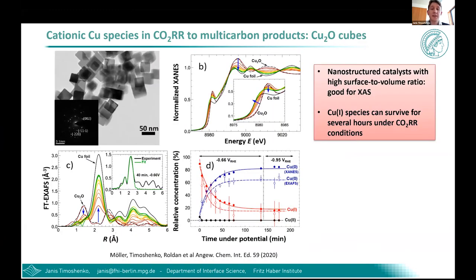That's why a follow-up study was quite instructive, which was also carried out on pre-oxidized copper catalysts for CO2 electroreduction, but in this case, these catalysts were prepared in the form of size and shape selected copper cubes. So in this particular case, the surface to volume ratio is much higher, so we are more sensitive to the surface processes when applying sample averaging methods like XAS.